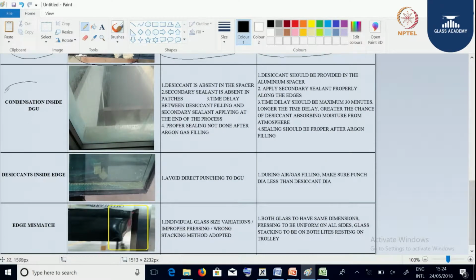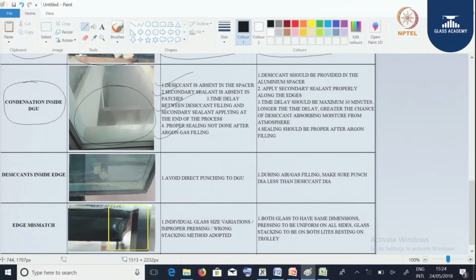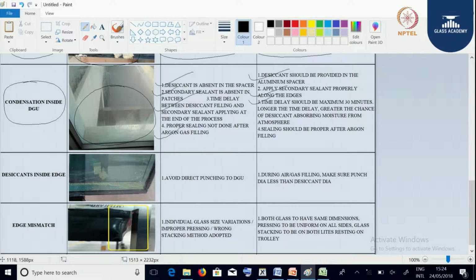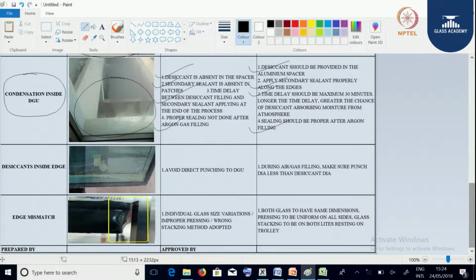The next defect is condensation inside the DGU, that is, moisture is trapped inside the DGU. The reasons are that desiccant is absent in the spacer, or the secondary sealant is absent in patches, or there is a time delay between the desiccant filling and the secondary sealant application at the end of the process, or proper sealing was not done after argon gas was filled. We can overcome these issues by providing desiccant in the aluminum spacer and applying secondary sealing properly along the edges. The time delay should be a maximum of 30 minutes; the longer the delay, the greater the chance of the desiccant absorbing moisture from the atmosphere. Sealing should be proper after argon gas is filled.